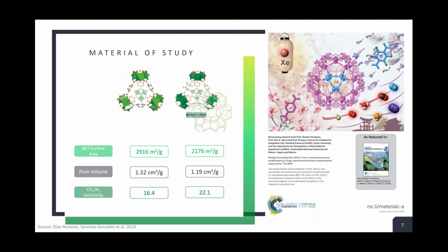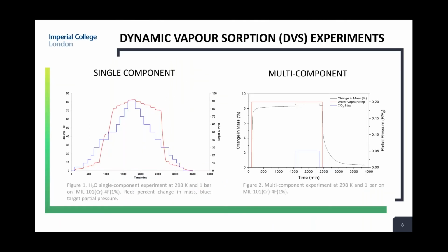Also, by incorporating fluorine atoms, they effectively increase the hydrophobicity of the material, which I will show you later in the isotherms. So we used a DVS Resolution from Surface Measurement Systems to measure and analyze adsorption and coadsorption of low concentration CO2 and water on the enhanced material and the pristine form. All the experiments were done at ambient pressure and temperature in an attempt to replicate real industrial conditions.